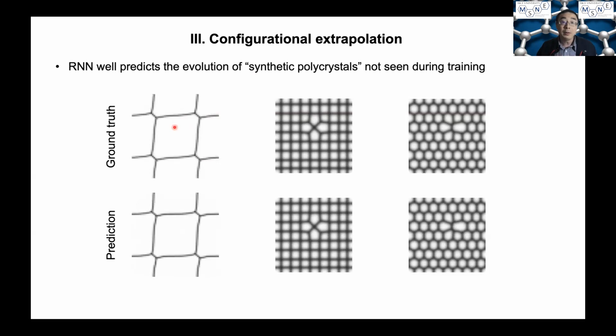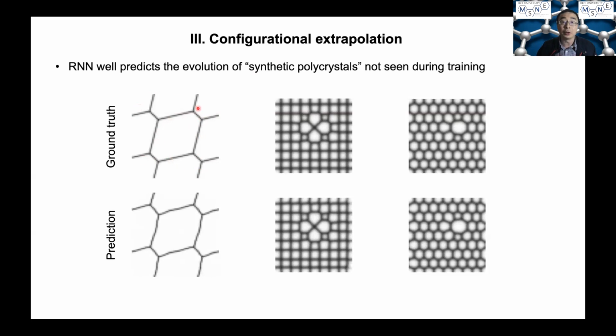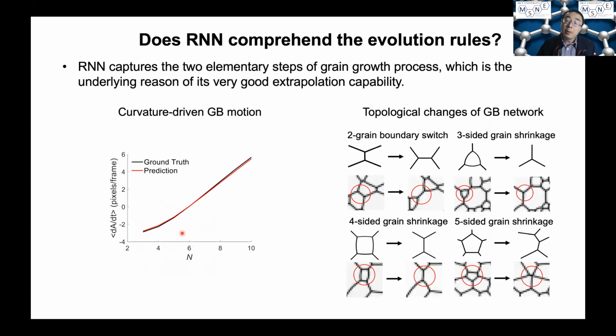But even though the difference is very significant, the model is still able to accurately predict which grains will disappear and which grains will survive and how the grain boundary network will evolve, and has very good agreement between the prediction and the ground truth. Okay. So we're very happy with all these tests that we posed to the machine learning model based on the convolutional RNN, and we think it passed the test.